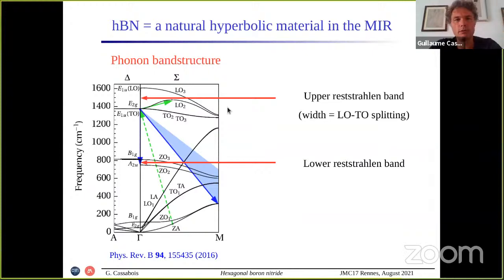ZO is nothing else than the transverse modes for the atomic vibration along the C-axis. So ZO and TO are transverse modes where the atoms vibrate either in plane for TO or along the C-axis for ZO. This is extremely important, and it is a direct consequence of the anisotropy, the fact that vibrations in the plane and along the C-axis give rise to eigenmodes that are spectrally separated.